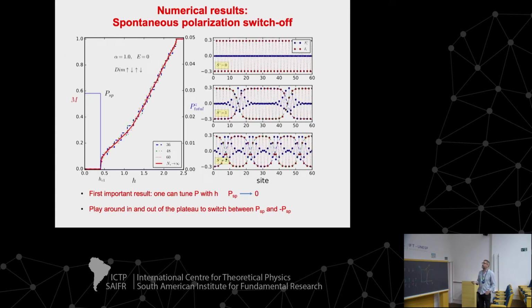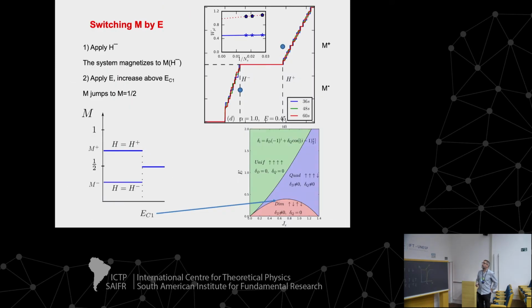So this is DMRG, so nothing new, but just to verify what we have obtained first by bosonization. You see you have here polarization going sharply to zero, while magnetization has important growth at the beginning and then goes smoothly. And this is the ground state, and these are one of the ground states, and these are the excited states where you see that these guys are like I described. Okay, so there are other issues that I will not have time for.